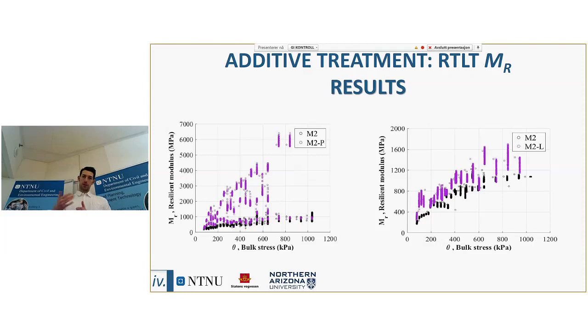So, as a further part of our PhD research, we wanted to make some modeling out of these experimental results. First and foremost, we tried to interpret this experimental data according to the models that are available in literature, the models that I mentioned before. In these following slides, we have two colors: the magenta color and the black color. The black color corresponds to the untreated material, while the magenta color corresponds to the treated material, whether with polymer-based or lignin-based additive. Again, in these slides we have two parts.